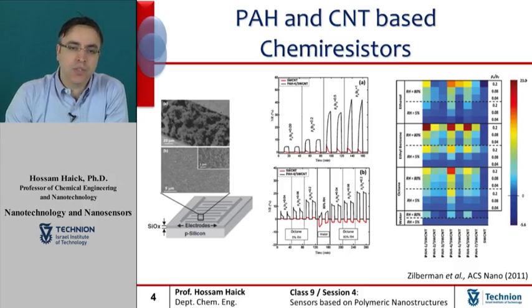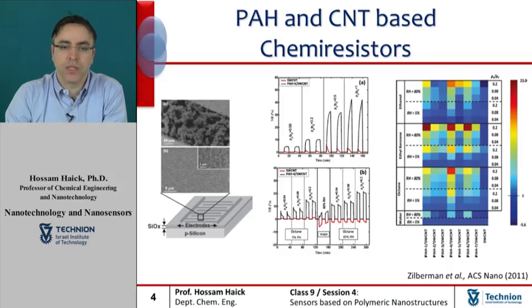In the middle figure, you can see sensor response to successive concentrations of hexanol diluted in synthetic dry air, octane diluted in both dry air and highly humid airflow, and the response to 80% relative humidity. The red curve in the figure shows response acquired by the pristine single-wall carbon nanotube sensor. The black curve in the figure shows response acquired by the PAH4 functionalized single-wall carbon nanotube sensors. Two repetitions were made to each concentration, and you can see that the addition of the PAH sensing layer greatly improves the sensing ability of each sensor and the array as a whole.